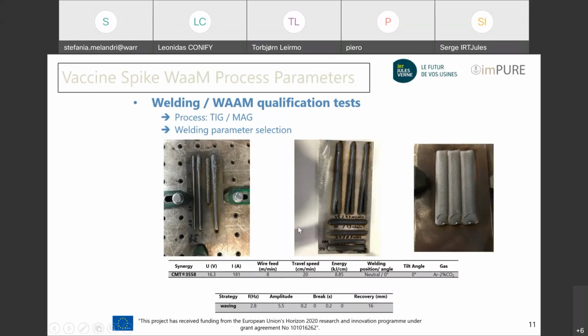And what is important also to have the overlay is that we can add the bead, or have a waving strategy to overlay and to have a better overlay. And here you see that the overlay is quite good. And at the end of the extension, we have a small collapse, and just to reduce the effect of the extension collapse, we add a transverse bead on the insert.